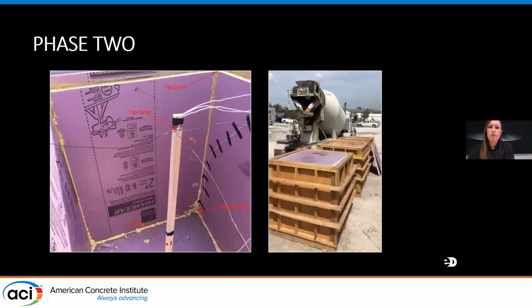In addition, a full-scale semi-adiabatic test with the shotcrete mixes was poured in order to verify the thermal performance characteristics and calibrate the thermal models on Concrete Works to later be able to add this to the thermal control plans that we had made for the self-consolidating and the conventional mixes. These cubes were 1 by 1 by 1 meter insulated boxes to represent semi-adiabatic conditions. And we had thermal monitoring devices installed at the center, top corner, and bottom corner.